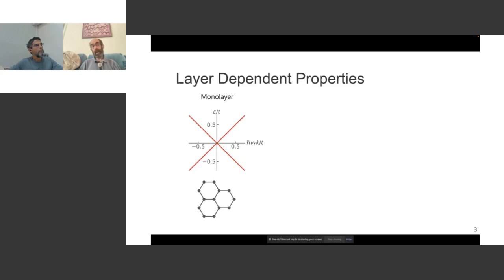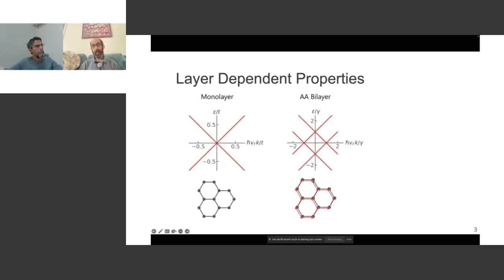But as I mentioned, this is not like graphite. And in fact, if you start putting layers together of graphene, you get different properties. So first, let me show you something that's imaginary. If you were to put two layers of graphene one on top of each other in a way that every atom sits right atop one other atom, then you would get a so-called AA bilayer, let me just leave it at that. And it would have a more complex structure with two copies of this energy linearly proportional to momentum, but the two are shifted to zero, having their zeros at different momentum. This is not a physically energetically favorable structure.